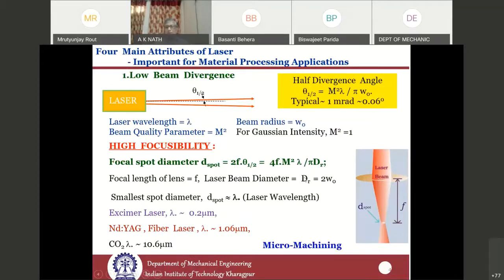And if you put the typical values, the smallest spot diameter you can generate is of the order of the wavelength of the laser. Now the lasers which are available, excimer lasers, having the wavelength in the range of 0.2 micron. So one can get 0.2 micron diameter here. When you have got Nd:YAG laser, which is around 1 micron, then the diameter of the spot will be 1 micron. And if you have got the CO2 laser, which operates at around 10 micron wavelength, the minimum diameter will be around 10 micron. So depending upon the laser wavelength and the beam quality, you can have very small spot diameter. And this focusability is very important for micro machining applications.